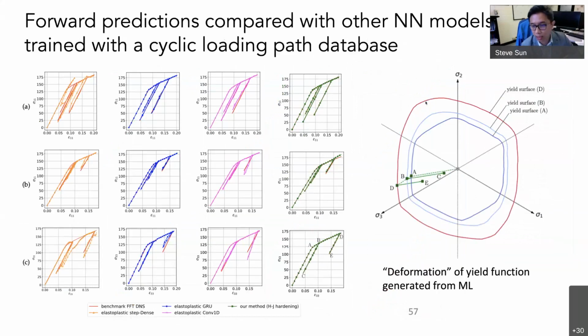This is more response. As you can see, the nice thing is not only do we get a more stable response, but you can clearly see that we increase the interpretability of the constitutive law. Here we know how the yield surface evolves, and that tells us something about the anisotropy evolution of the yield surface. And we can also check whether the yield surface is thermodynamically admissible by simply checking whether it has the convexity required for a stable or physically compatible model.